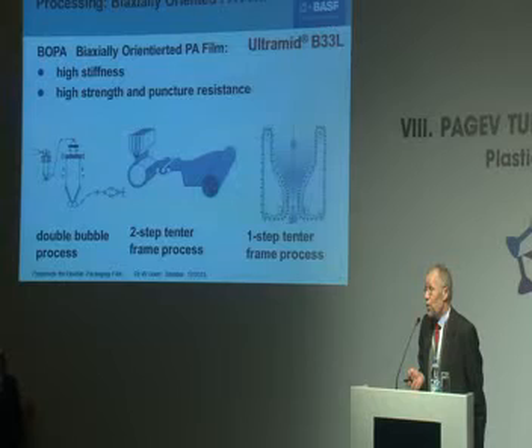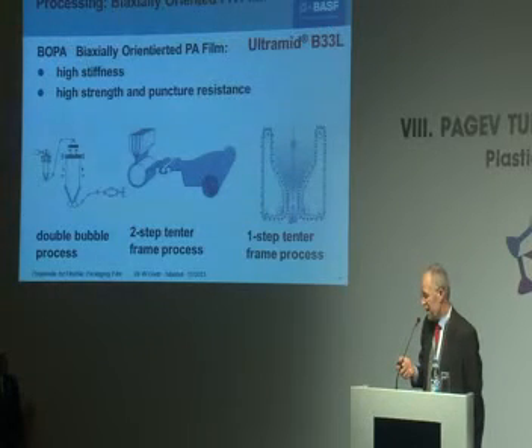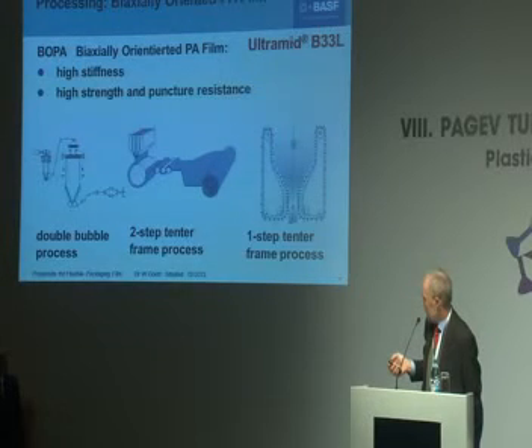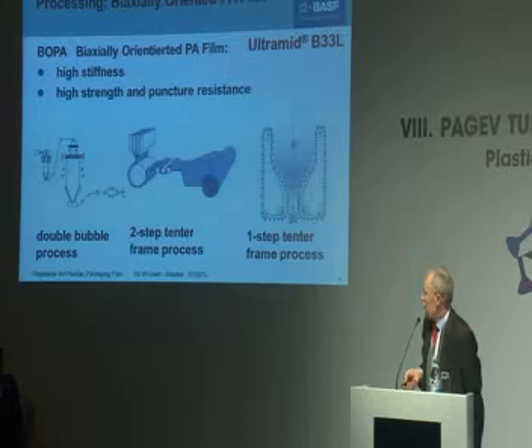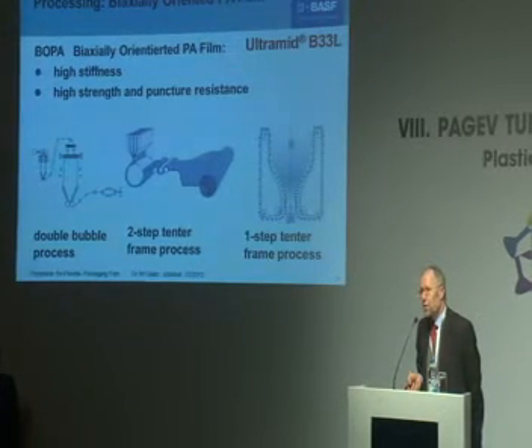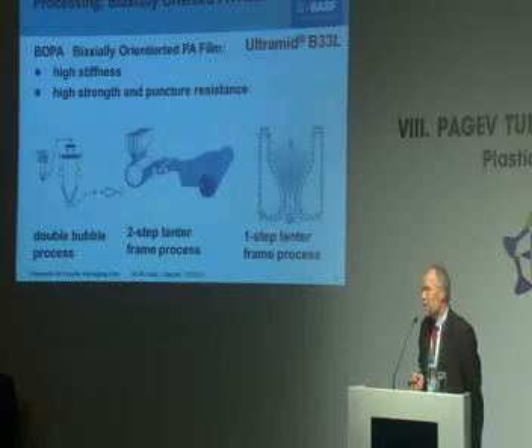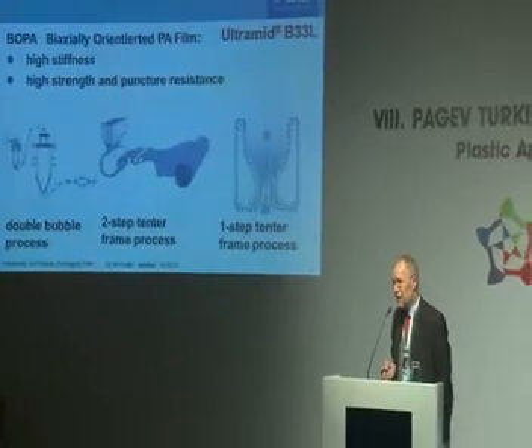And polyamide is also used for manufacturing of biaxially oriented film. It's transformed by all three technologies that are available for biaxial orientation: the double bubble process for a blown film; the most common, most frequent technology, the two-step or sequential tenter frame technology, where the film is extruded to a cast cylinder, then stretched in machine direction and finally in the transverse direction; and also the simultaneous or one-step tenter frame, where the cast pre-film is stretched simultaneously in both machine and transverse direction.